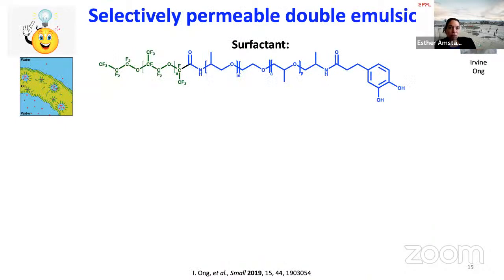And so to me, a possibility to suppress that was to reduce the mobility of the surfactants, to prevent them from desorbing from the interface and forming these small drops. Yet I didn't want to covalently cross-link them, because if you covalently cross-link them, you form a rather rigid shell that, if it breaks, is broken and the capsules become leaky.